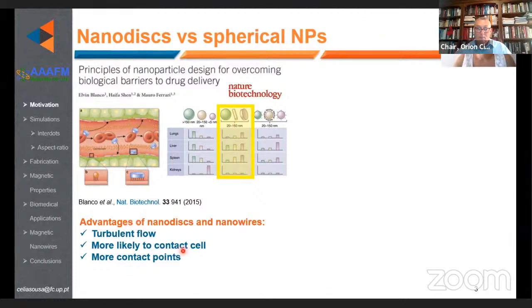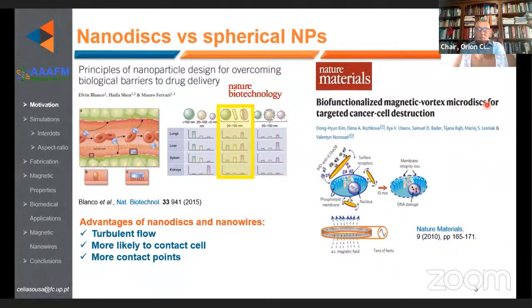In particular, nanowires and nanodiscs showed several advantages compared with the spherical counterpart, namely regarding the increased turbulent flow, the increased contrast with the cells, the increased contact with the cells, as well as the reduction of organ accumulation depending on their shape, size, and also the surface charge. So, recently, magnetic nanodiscs in a vortex state showed the ability to perform cancer cell destruction by a mechanical movement under low magnetic fields and low frequencies.